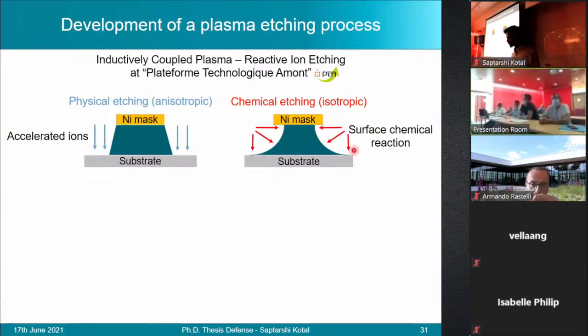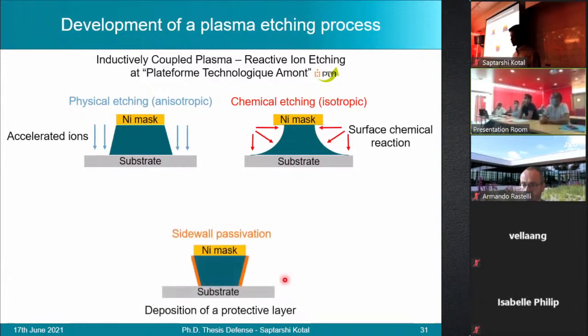The second process is the chemical etching, which is isotropic in nature and relies on the reactive ions reacting with the surface of the sample, generating volatile materials which leave the sample, thereby etching it. And the third process consists of sidewall passivation, where we see the emergence of a protective layer on the lateral facets of the device, which prevents further chemical reactions.